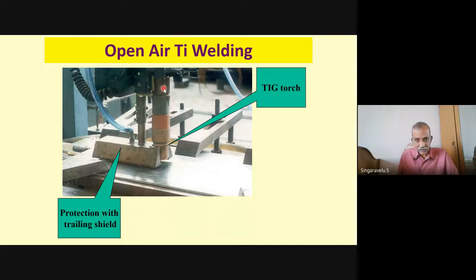TIG. So this is the TIG torch. See the 100% shielding there. This is the trailing shield, which we have been holding. This is the direction of welding, from left to right. Okay, so once the welding progresses like this, the already deposited weld, including the HAZ, is protected up to 300 degrees centigrade by supplying the argon shielding. This is the one. Since it's a bead on plate welding, underneath no purging is required.